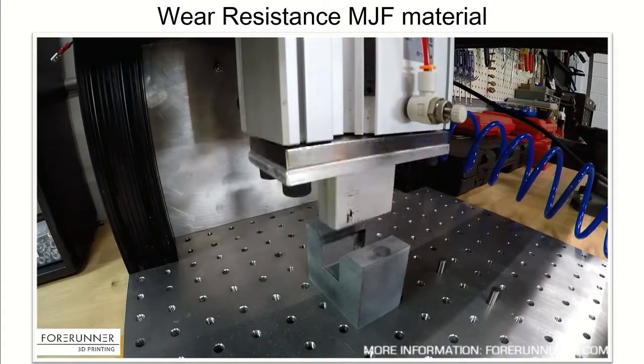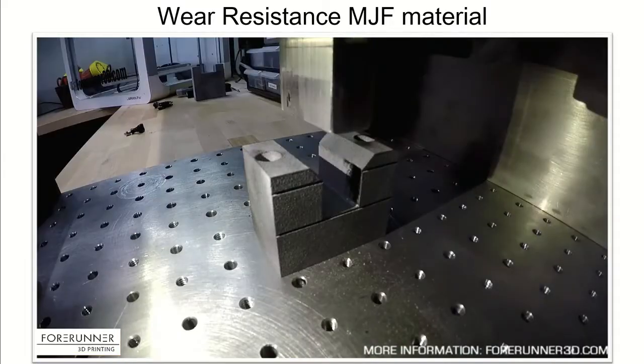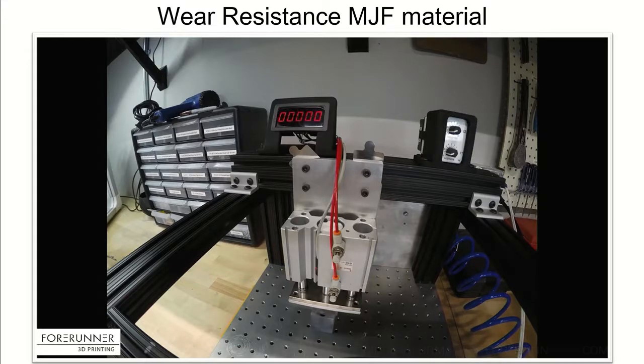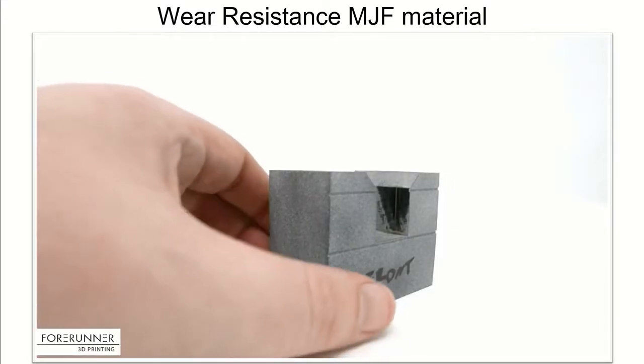So we built this 80/20 frame, aluminum jig plate with a bunch of dowel holes and bolt holes drilled into it. This detail that we're testing, this MJF detail, is actually sitting back at the back of the room there. So feel free to check it out at the end. We put it in, we lined everything up on this 80/20 frame, tightened it all down, and then we loosened the bolts on the cylinder, and we put 10 thou misalignment shims behind the cylinder to actually move the cylinder out of position. So it created about a 7.5 thou interference with that nest. And then we hit it 100,000 times.